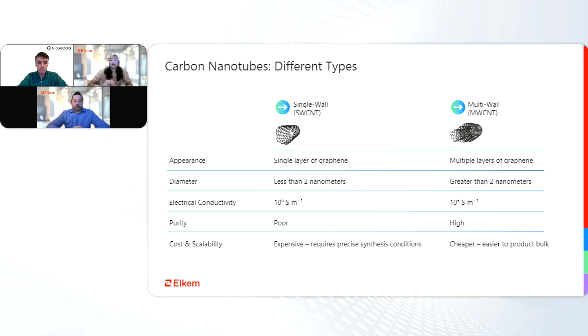Single wall are single layers of graphene that are less than 2 nanometers and have a conductivity of around 10 to the power of 6 Siemens per meter. These are relatively expensive to synthesize since it requires such a high level of precision. While on the other hand, multi-wall carbon nanotubes are more forgiving in making.